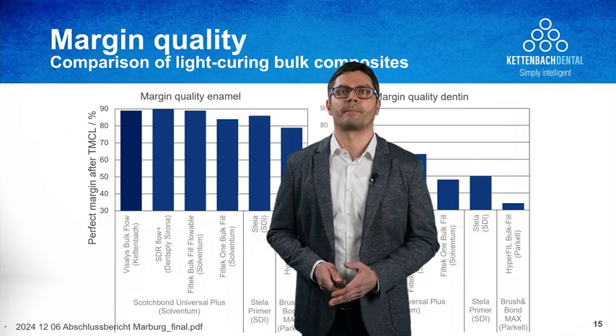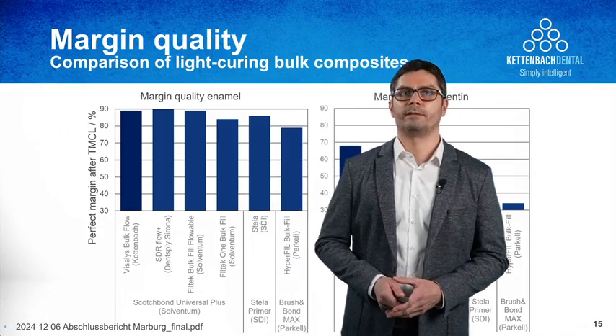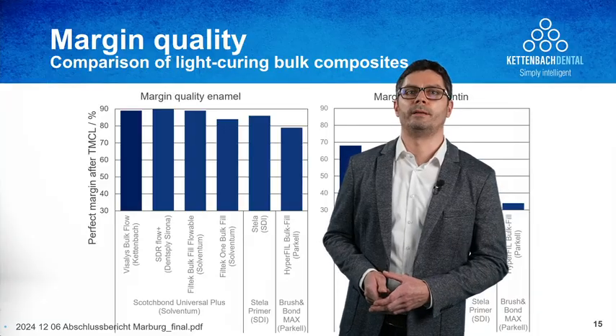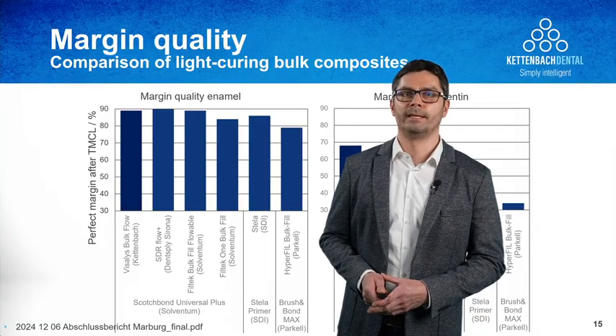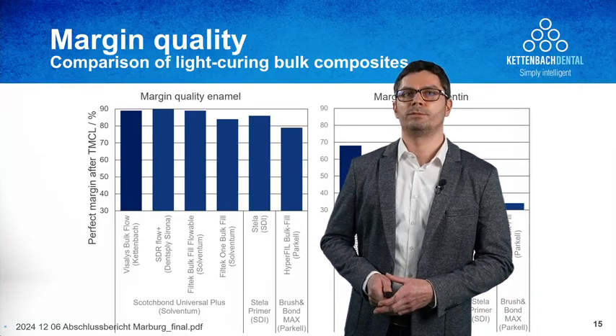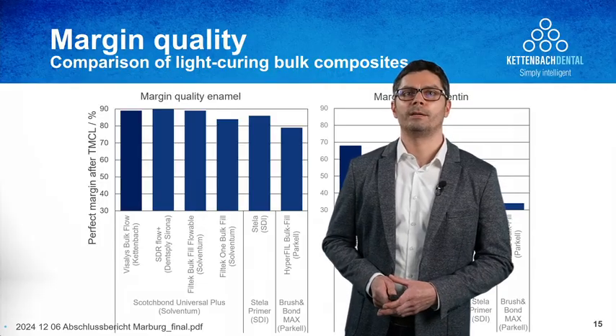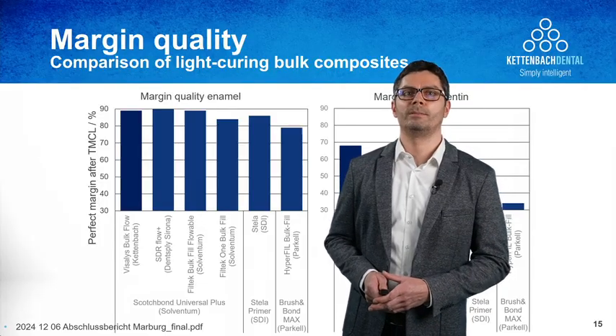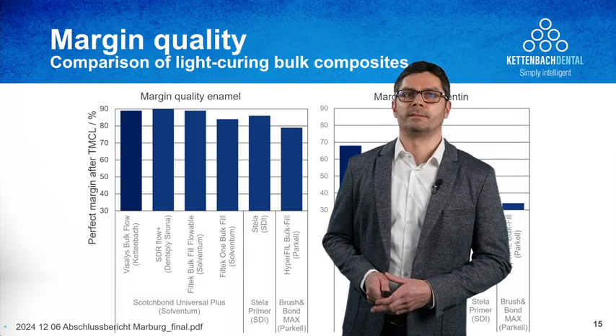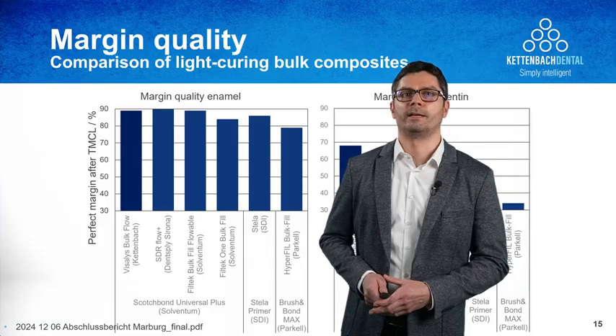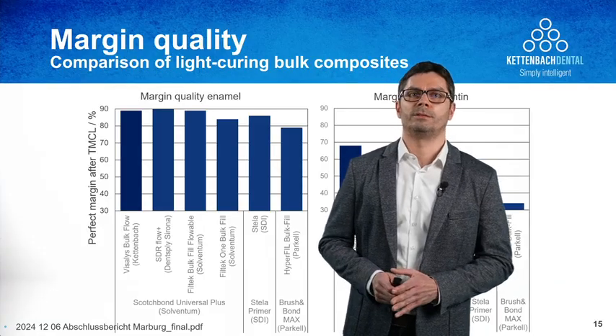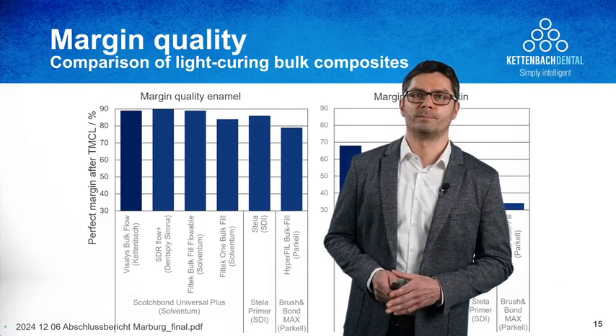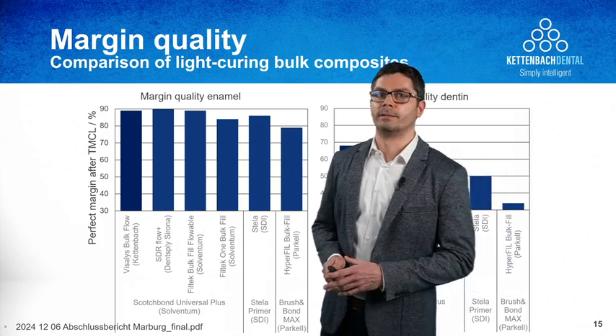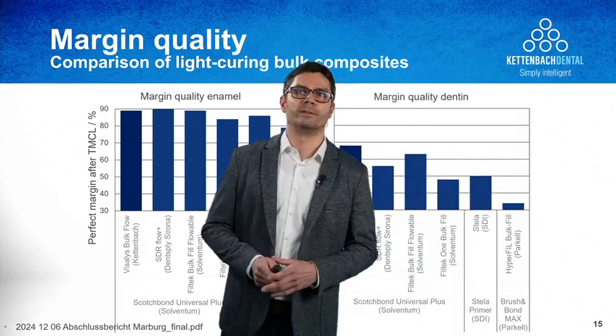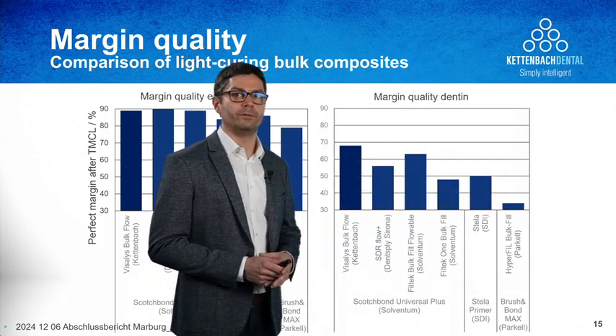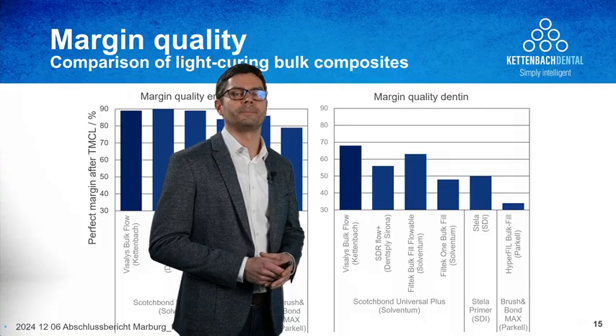That's obvious. So if you have a look at the first results for the margin quality on enamel, you can see that most materials do have a more or less high quality of margin on enamel, but Visalys Bulk Flow has one of the highest values. It's not that hard to get a good value on the enamel surface, but it's even harder to get a good performance on the dentin part of the tooth, as you can see on the right hand side.